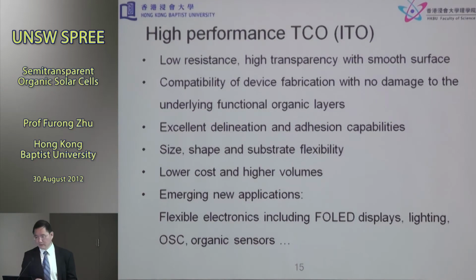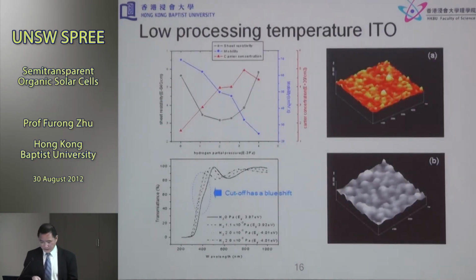So we actually spent a bit of time to develop this technique for various applications. The technique is called low processing temperature. Currently, I believe that some of your researchers may have already used ITO coated glass substrates for your solar cell fabrication. But ITO coated glass that you purchase from vendors is basically deposited using a sputtering process or magnetron sputtering process at a high temperature, around 200 degrees Celsius, if you want to have a good ITO film on a glass substrate. But this technique cannot be used for organic solar cells. We know that these organic materials cannot be prepared at such a high temperature. So we developed a technique called low processing temperature, and essentially it operates at room temperature, so it is compatible with the organic semiconductor materials.